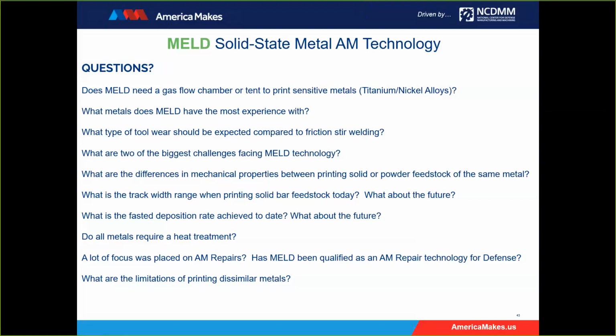And on the other side of that, when the demand's there, we'll go up to a 1/2 inch square feedstock, and that essentially doubles our deposition rate from, I use aluminum as an example, from 30 pounds an hour to 60 pounds an hour.